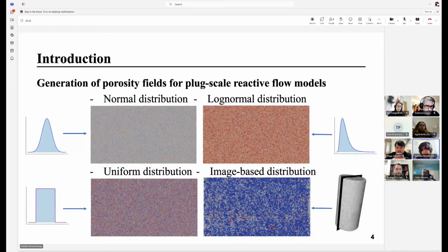And this type of model needs initial information to initialize it. In the literature, we see a lot of methods to initialize this information. One of the pieces of information needed is a porosity distribution to simulate the real rock porosity. We have ways to initialize a field. In the literature, we normally see normal distributions, log-normal distributions. Uniform distribution is very used too. And we can use image-based distributions, which we try to employ here.